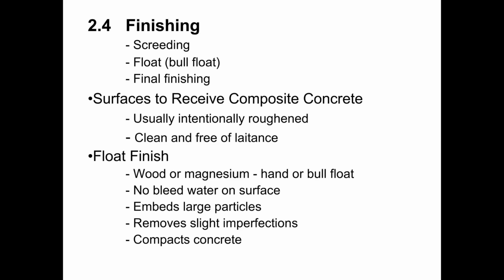We don't want to wait so long to do the roughening of that surface that the roughening actually just pulls coarse aggregate particles out of the surface of the concrete and then leaves them loose on the surface. That would be laitance. We want to do the raking fairly soon after the floating process. The concrete needs to be stiff enough that it will hold the rake, but not so stiff that we're actually pulling coarse aggregate particles out of the surface of the concrete, leaving loose material behind.